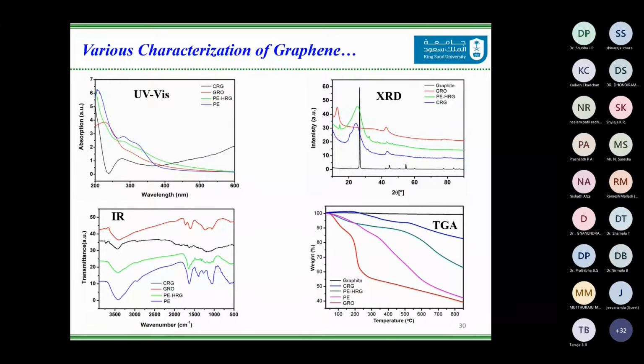Once we subjected the reaction mixture, which is evident in green, P is the plant extract and HRG is highly reduced graphene. So in P-HRG, if you see, these two peaks that appear around 230 and 301 disappear. You will see that there is a disappearance. However, in chemically reduced graphene, you will see a peak at 271. This is the black one.